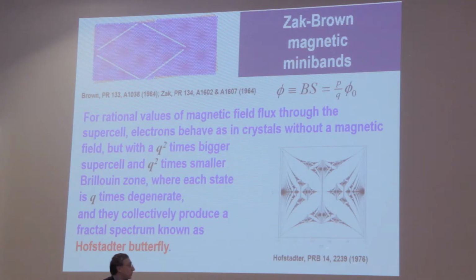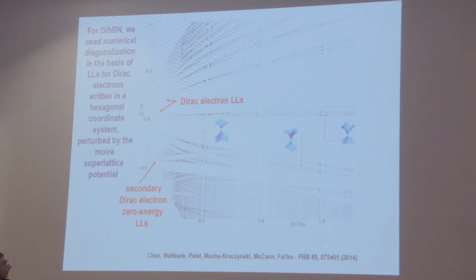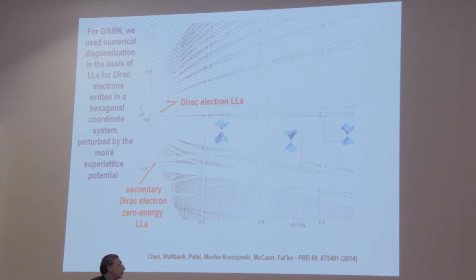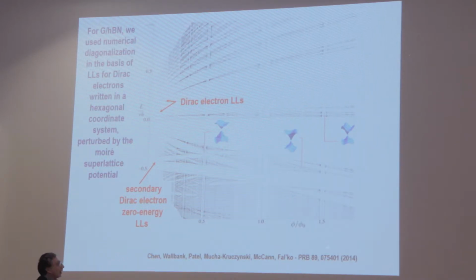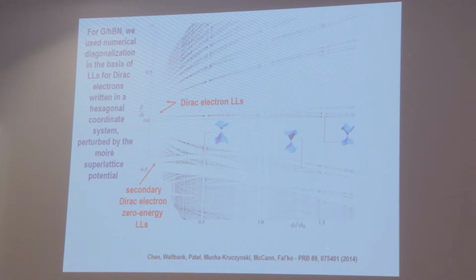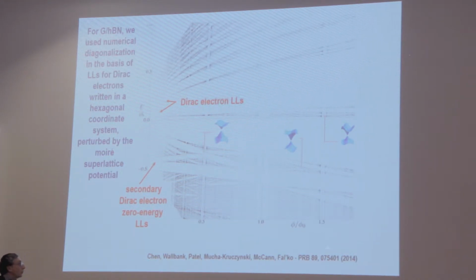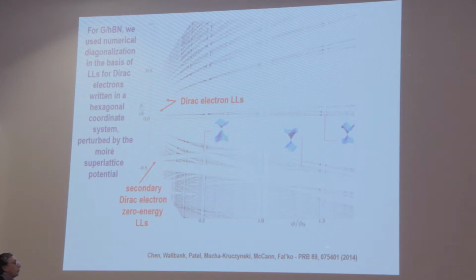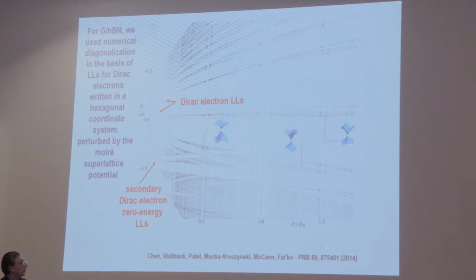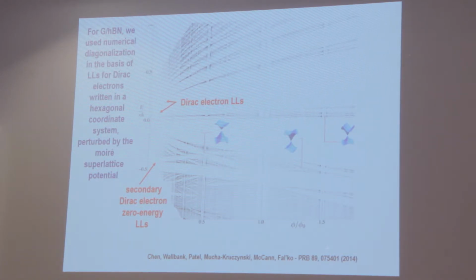And this is exactly what collectively produces a fractal spectrum known as the Hofstadter butterfly, illustrated for the tight-binding model on a square lattice by Hofstadter. So what we had to do here was that we needed to use the continuous model. The tight-binding model doesn't really help us here at all. And we had to use some bases. And what we did, we adjusted the basis we used to the symmetry, the hexagonal symmetry of the superlattice. So we used a non-orthogonal coordinate system, and we used the Landau level basis for this, and then we used the superlattice